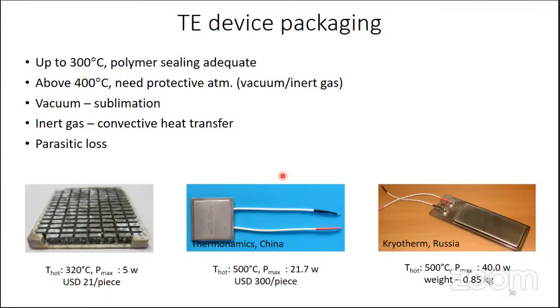Coming to the packaging I was talking about: now you have a stable hot side contact. The cold side is not a high temperature, so it's not going to be any problem. But how to protect the leg? If it is low temperature, 100, 150, 200, it's not a big issue. You can put a polymer and protect it like this. But above 400 degrees Celsius, like the device I'm talking about, no polymer can withstand up to 400 degrees Celsius. So what to do? In that case, you have to do hermetic sealing. There is no other option.